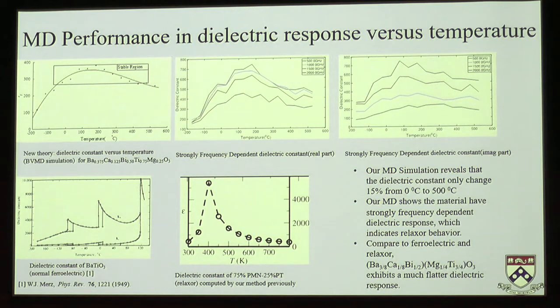So the take-home message in this slide is our classical force field can reveal the flattened dielectric response. And it also gave us the frequency-dependent behavior. Such frequency-dependent dielectric response is also an indication of relaxor behavior.